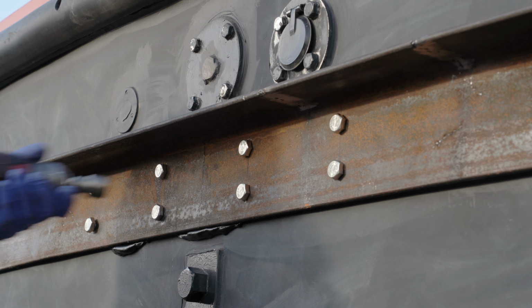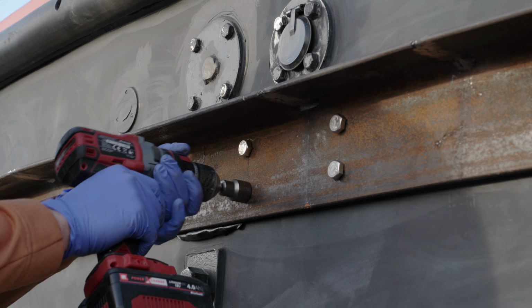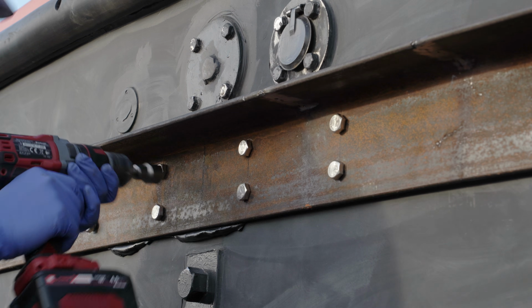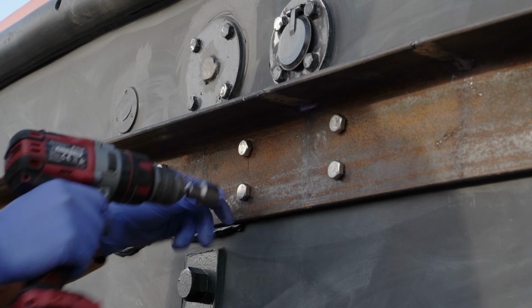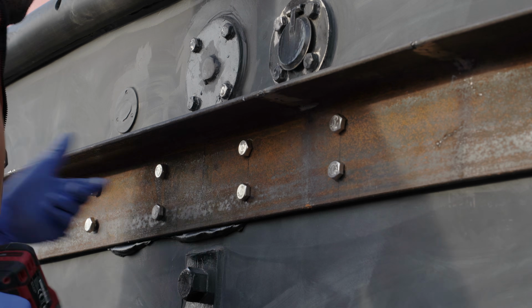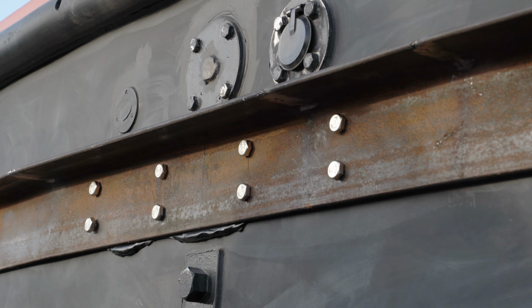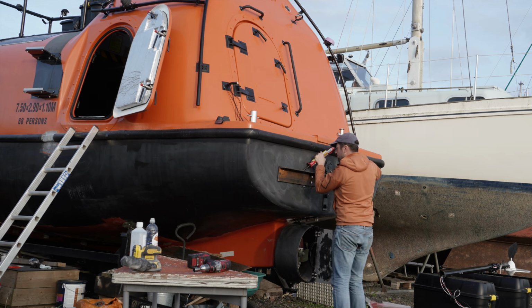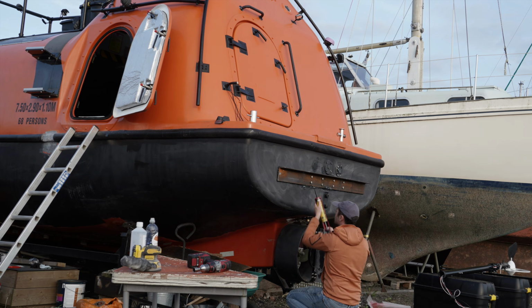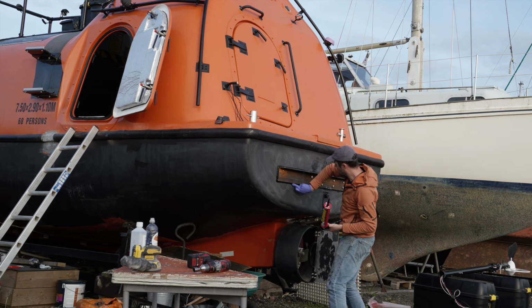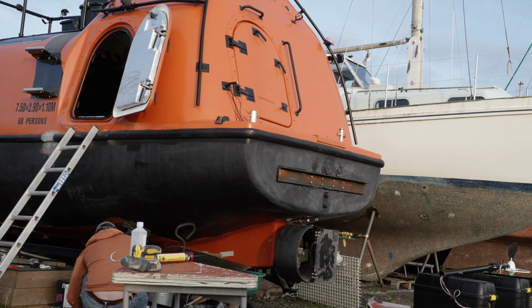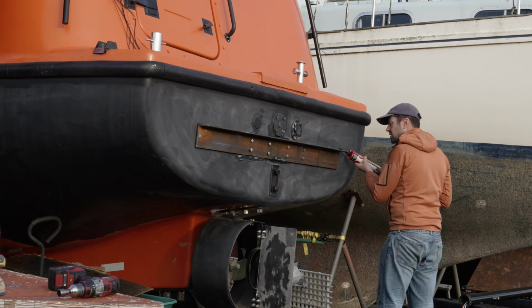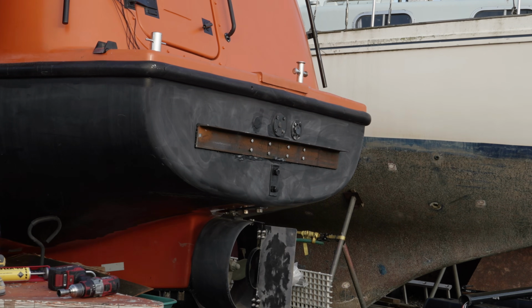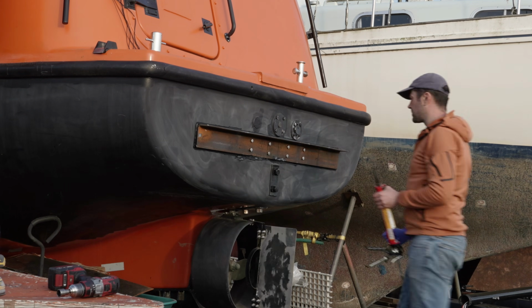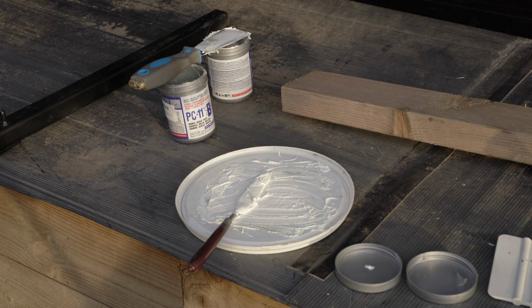The tightening causes a little oozing, which is fine, and in one small area a little epoxy adhesive has emerged, which isn't what I wanted, but I think will survive. In some areas the pre-squirted sealant hasn't oozed out, so we'll need some more sealant added around the 4 sides so it's a strong, thick, liberal seal. Water getting around the back, even with the tight fit and with all that epoxy, will attack the steel, and we don't want that. Once cured after a couple of days, I can apply a nice neat coat of epoxy primer and top coat before mounting things to it.